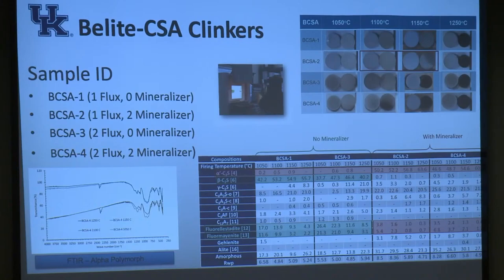But we can take that, so in this table here that I don't expect you to be able to see, 1250 is our standard CSA operating temperature. So we are producing some of our cements around 1050 degrees Celsius. It doesn't seem like much, but it's actually quite a big deal if you're looking at the amount of production a cement industry goes through. And then the novelty that comes out of that is looking at some combinations of a flux to create a melt at a lower temperature, and then a mineralizer to stabilize those phases at that low temperature. And we were able to do that. It was fascinating. And Belite, if you didn't know, has three different polymorphs, an alpha, beta, and a gamma. The alpha form is the most reactive form. So we made sure to engineer our Belite with that alpha polymorph.